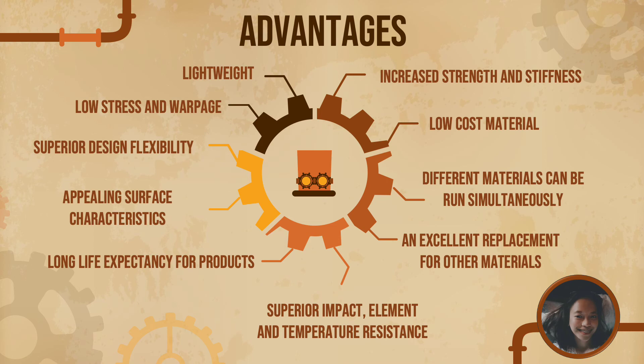Less energy and materials are used, resulting in energy savings. Lastly, increased strength and stiffness: the structure within the parts gives them very high strength-to-weight and stiffness-to-weight ratios. It can achieve between 10% to 30% weight reduction without affecting structural integrity. In addition, structural foam is up to 8% stiffer than similar solid polymer materials. Since it is foam, the material also makes for a great thermal and acoustic insulator.